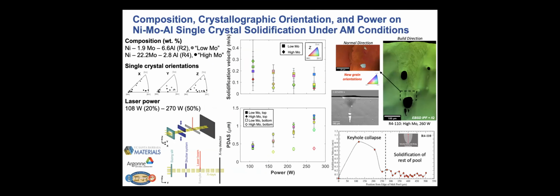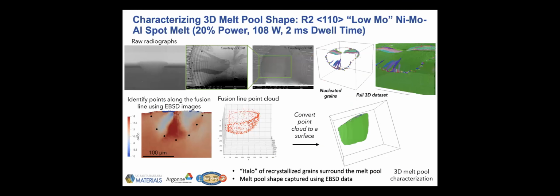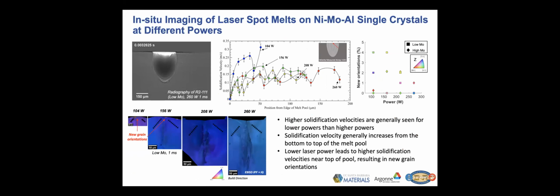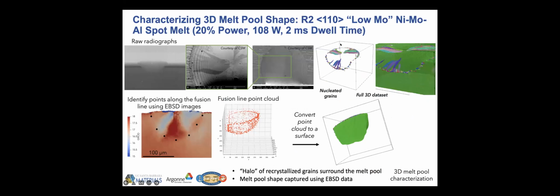Yeah, so the halo that we're seeing. What we think happened there is that, in fact, you can see here our grinding layer, like when we make these thin 100 micron, 200 micron thick cross sections for the APS experiments, we grind front to back and then on the top as well. And here we actually have ground the microstructure. And so that allows you to have strain present in the material, that when we hit it with the laser in this example, we end up basically in the heat affected zone and at the fusion line having that recrystallization happen right there. We actually are able to form that halo of the grains, and it's happening at the top surface where we have that deformation layer. And then we see the epitaxial growth of some of those grains at the top, across the melt pool surface.